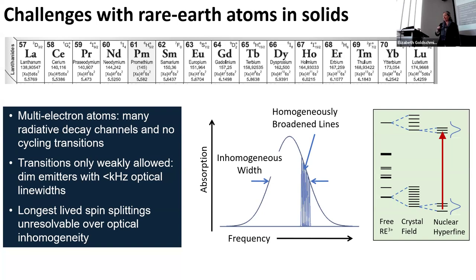the inhomogeneous broadening. So I said it was small on an absolute scale, and on an absolute scale, it is small. Unlike, say, NV centers where each one just looks different, ours are all packed to within, say, a gigahertz or so. But a gigahertz is big compared to the homogeneous line width of a kilohertz. And for the really long-lived nuclear hyperfine states in europium, which is the one with the 6 hour coherence time, those splittings are, say, tens of megahertz. And so even my still small inhomogeneous broadening washes them out.